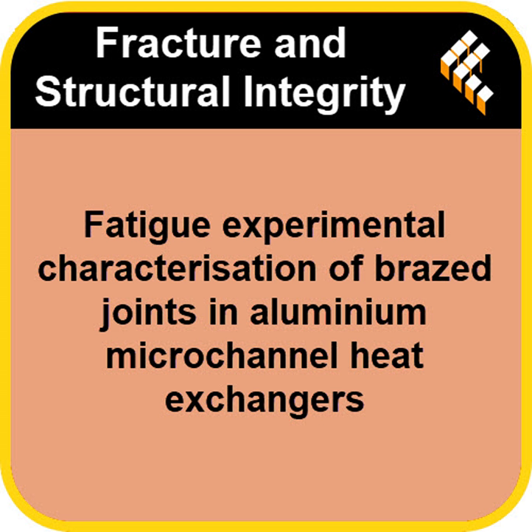60 MPa. Now, help us put that number in context. You mentioned the base materials might have strengths closer to 90 or 100 MPa, maybe more, even after the heat treatment. 60 sounds quite low in comparison. It is relatively low, yes. And that's the whole point, really. That 60 MPa represents the maximum range of cyclic stress that this joint can handle, essentially indefinitely, without failing. So in the real world, if a heat exchanger in, say, a commercial chiller operates below that stress level at the joint toe, it should theoretically last for that 10 million cycle target, which could easily be 10, 15, maybe more years of service.